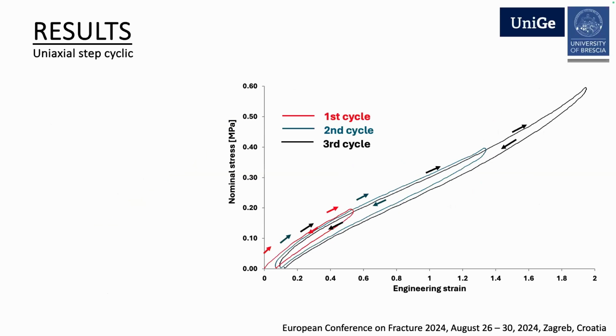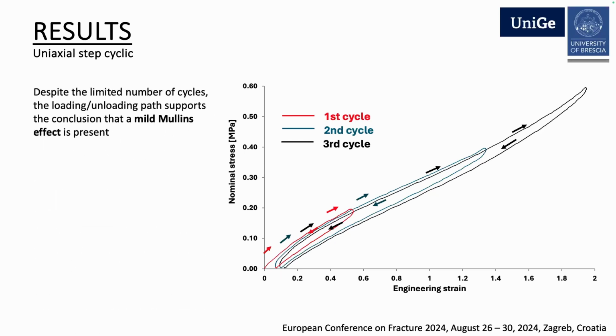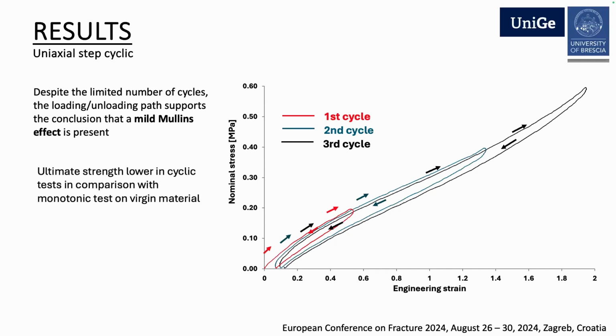If we look in more detail at the loading and unloading paths during this very first cycle, we can see that there is a sort of Mullins effect. I would say it's rather mild, but what you see is that when you unload and reload the specimen, when the specimen reaches the peak stress that was applied in the previous cycle, then apparently it follows the same curve as the virgin material. From a modeling point of view, I would say this is a secondary effect that maybe is not so necessary to include in a model.